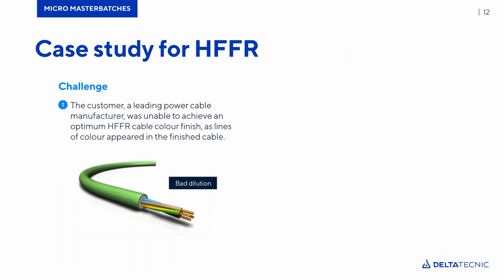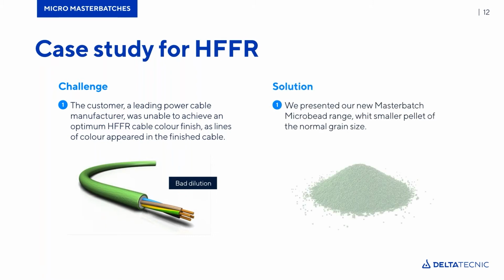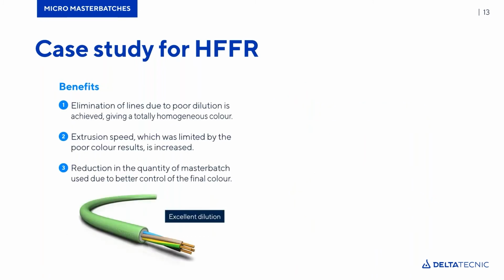Then the other case study, here we are talking about HFFR cable. You know, these flame retardant halogen-free systems at the compound, they pose also a challenge in terms of color. They sometimes put difficulties on the dilution process. And in this case, it was a very big global player with over 100 factories worldwide, who is active in all kinds of cables: high voltage, submarine, telecom, energy, building wire, special cables, automotive, in all sectors. And in this case, we're talking about this HFFR cable with a green color, and they had these waves on the surface, these lines, this color irregularity. And we presented again the microbead in this case, because this was a polyethylene-based outer sheet with a smaller size. And again, the same results were reached.